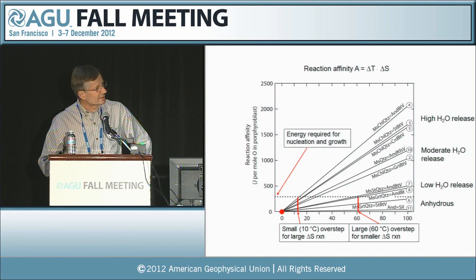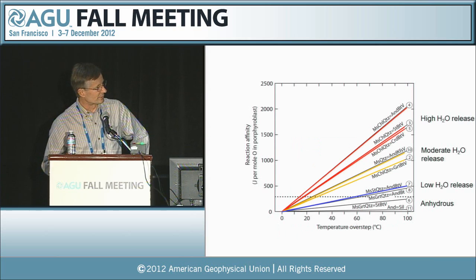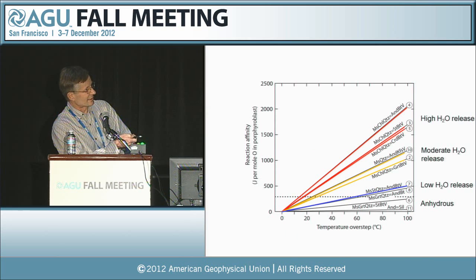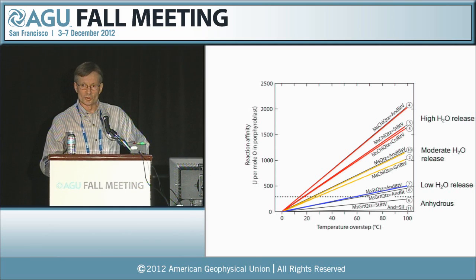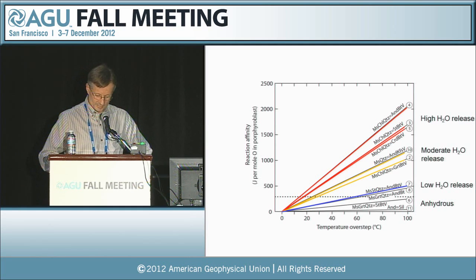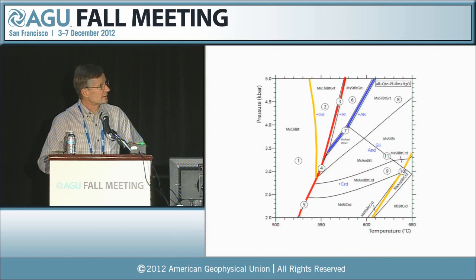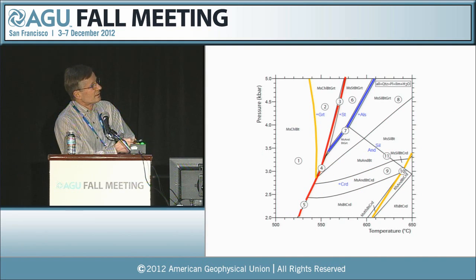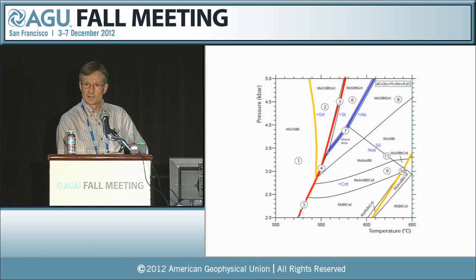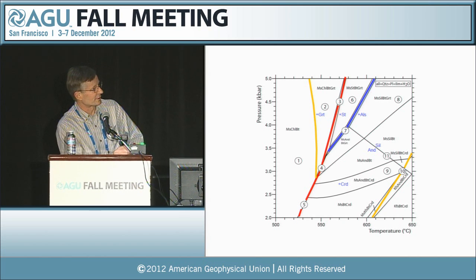So I've taken these curves and color-coded them. The highest entropy reactions are in red, these are intermediate in yellow, and lowest in blue, and I put them back onto the phase diagram here. So you can see that there's this big red band here. This basically corresponds to the consumption of chlorite, which disappears over a fairly small interval and is a very high entropy reaction because it releases so much water.